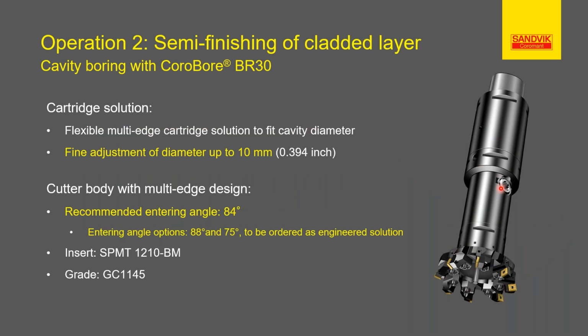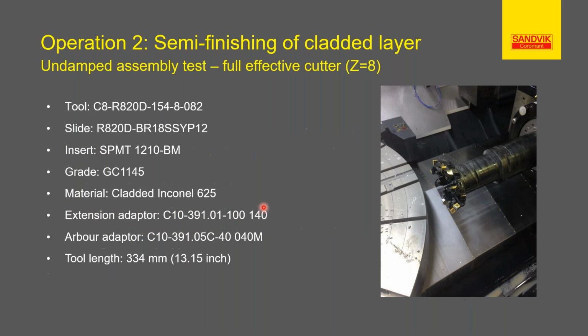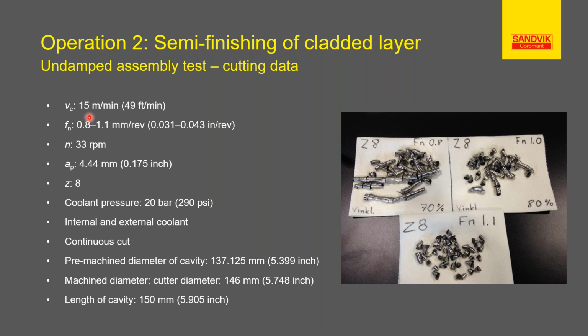You can see here we have an adjustment of up to 10 millimeters. We have several entry angles, but we recommend as first choice 84 degrees. And here you can see a real example. In this case we have 8 inserts on an undamped assembly. You can see here that the tool length is 334, so very long, but it is undamped. And you can see the results with 15 meters in speed. We moved the feed from 0.8 to 1.1, and 1.1 is the best solution for the chip, as you can see. Very small, perfect chip.